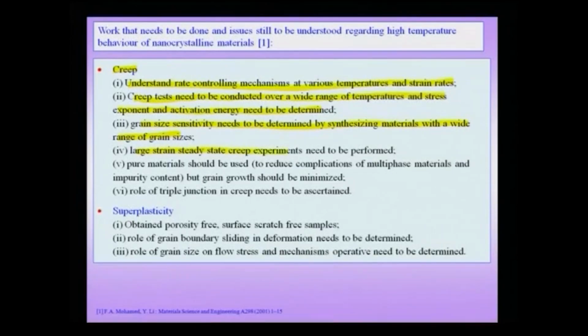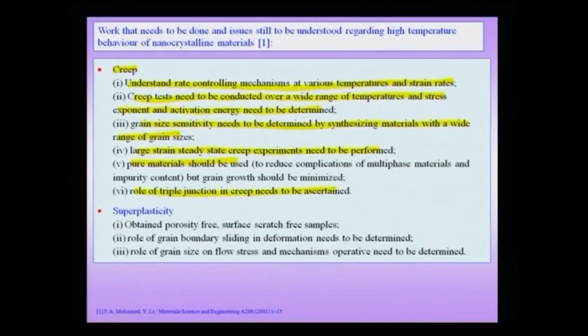Large strain steady state creep experiments need to be performed, which is another area where a lot of work needs to be done. Pure materials should be used, because in multi-phase materials, as we have seen in a few examples, though there is an advantage in using them because grain growth is small, understanding the underlying mechanisms becomes difficult. The role of triple junctions in creep also needs to be ascertained. We have already seen that triple lines and quadruple junctions are all very important in nanomaterials, but their role is poorly understood when it comes to creep.